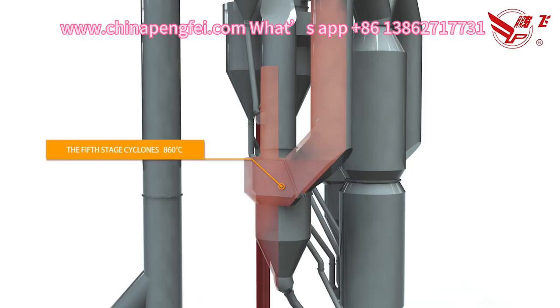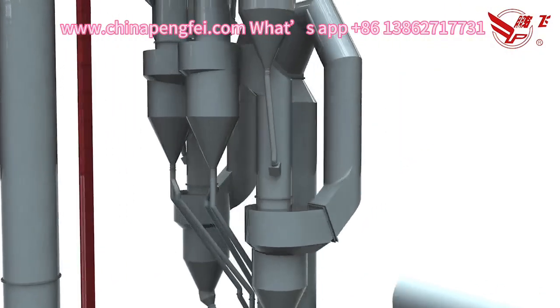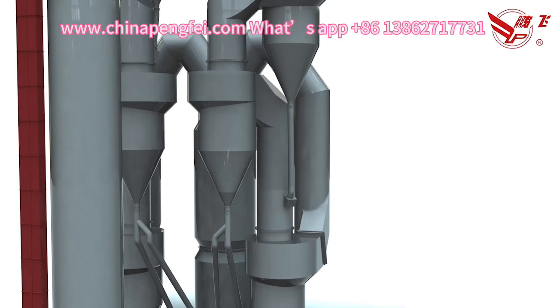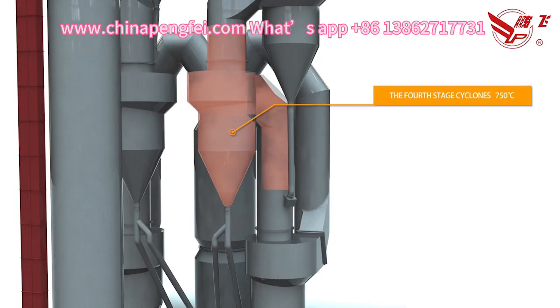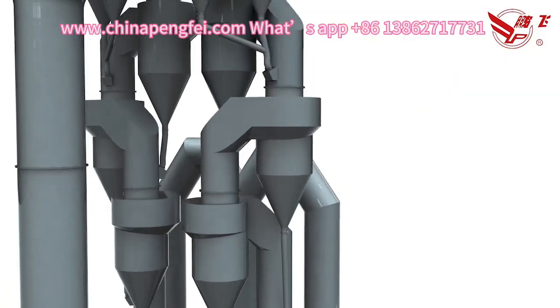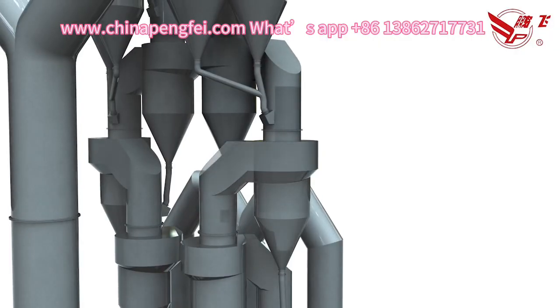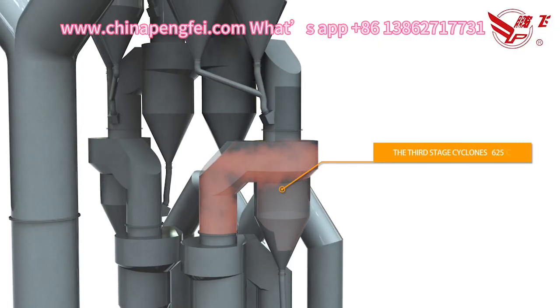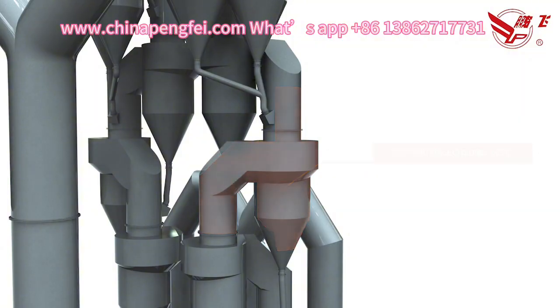The hot air temperature inside the fifth stage cyclones is about 860 degrees Celsius. High-speed hot air flows upwards and enters the fourth stage cyclones. The hot air temperature inside the fourth stage cyclones is about 750 degrees Celsius. High-speed hot air flows upwards and enters the third stage cyclones. The hot air temperature inside the third stage cyclones is about 625 degrees Celsius.